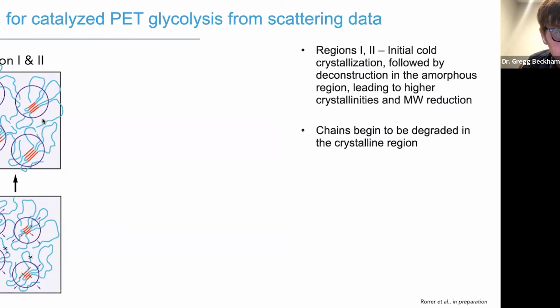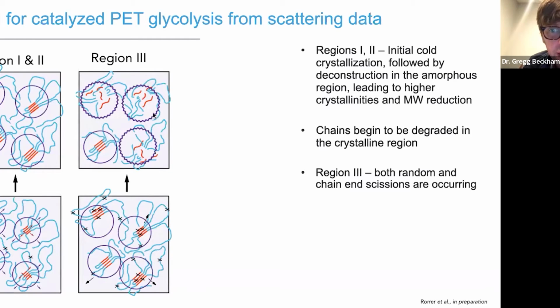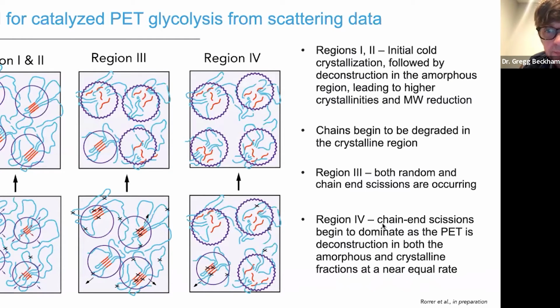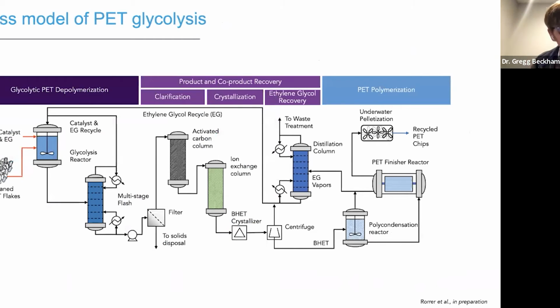And so in regions 1 and 2, this is essentially at the start of the reaction, you have these crystalline regions and these amorphous regions shown in red and blue respectively. You have some initial cold crystallization, and this is followed by deconstruction in the amorphous region, where the crystalline regions are still intact. But this leads to a really rapid drop-off in molecular weight and an increase in crystallinity. And then during region 3, the chains start to be degraded in the crystalline regions, so you're getting cleavages in the crystalline regions. And then at region 4, this is basically now at high conversion extents. Instead of random chain scissions, this is when we think we're starting to see chain-end scissions, as the PET deconstruction occurs in both the amorphous and crystalline fractions at an equal rate. And so that's a molecular picture and a macromolecular picture of this process.